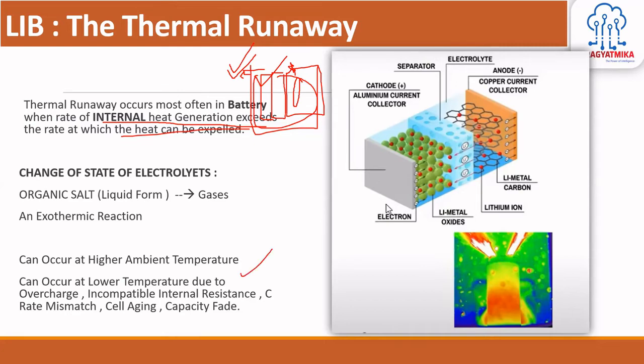It might occur at lower temperatures also. If the battery pack is at a lower temperature, your internal resistance is at a higher end, and then you do a higher C rate of charging. You are doing the CCCV charge. Maybe your battery pack is at 5 degrees centigrade, so at that time the internal resistance is higher. And then you have just started the CCCV charging, maybe with 5 amperes of charge. That will lead to an increase of the temperature within the cell. The cell internal temperature will increase due to the internal resistance.